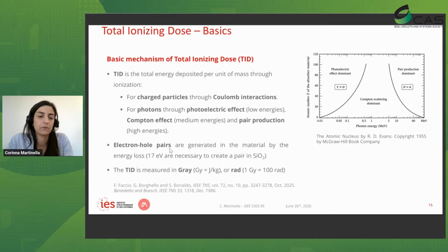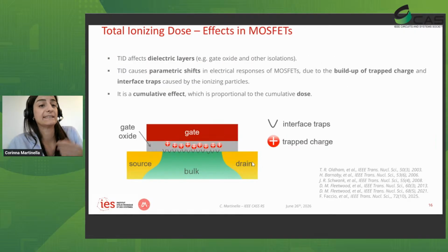For example, 17 electron volts are necessary to create a pair in silicon dioxide. The total ionizing dose is measured either in gray or in rads. In this presentation, we will use rads, and we can say that 1 gray is equal to 100 rads. The total ionizing dose affects the dielectric layers, such as the gate oxide and other insulation layers.